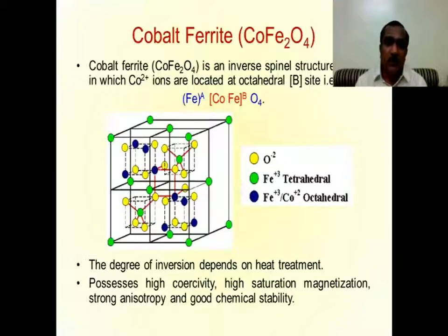So we chose the cobalt ferrite material for our study, and cobalt ferrite is an inverse spinel structure. Inverse spinel structure means the cobalt metallic ion is occupied at the octahedral B site, and the Fe ions, that is two Fe ions, are distributed equally at the tetrahedral A and octahedral B site. The structure of this cobalt ferrite is shown here, and it is inverse spinel.